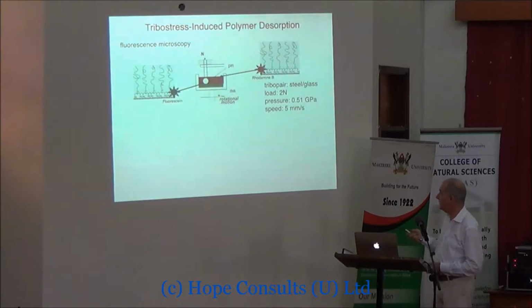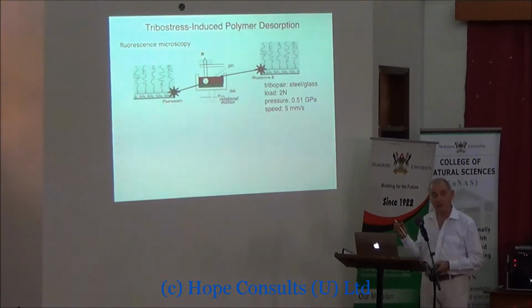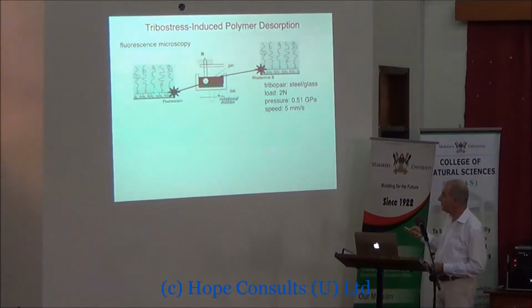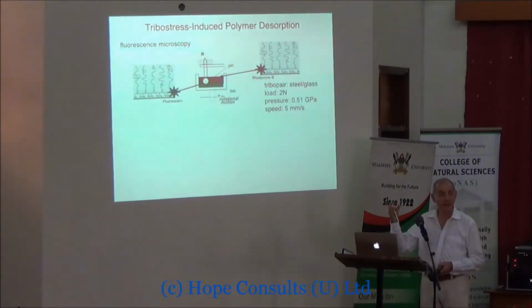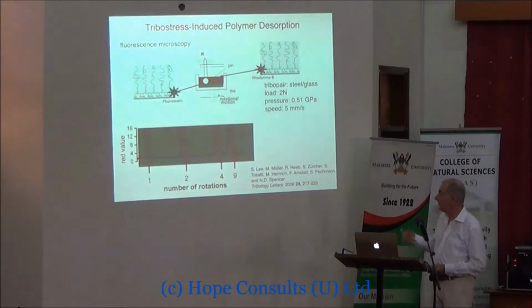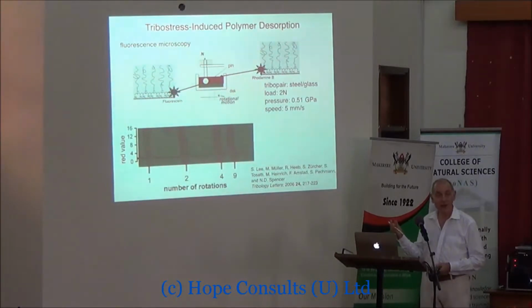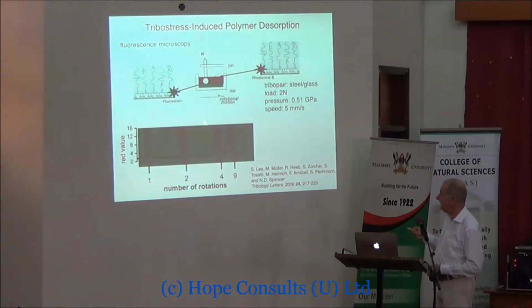And so what's happening, we wanted to investigate more closely, and we used fluorescent labeling in order to do that. We put a green label on one batch of the polymer and a red label on the other one. We adsorbed the green label polymer on the surface, and we put the red label polymer in the solution. We did the pin on disc test, and as we did more and more rotations, more and more red came into the track where the pin had been scraping. In other words, what happens is it heals itself.